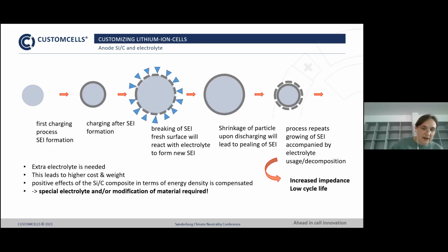On the anode side, on the other hand, silicon, which is a trend, shows a very high volume change upon charging and discharging. And there is a so-called SEI that is formed upon formation. This is a solid electrolyte interface that prevents the solvent molecules from intercalating into the material. Because the silicon has such a high volume expansion, this SEI will break, and new electrolyte molecules can react with the now bare silicon surface and build new SEI. And upon discharging, the particle will shrink again, and the SEI will be on top of this layer.